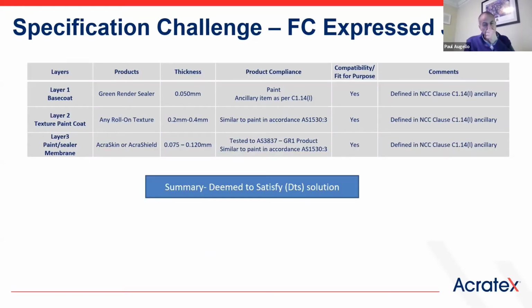The last one is the express jointed system, and this has probably got the most flexibility of all the substrates that are on the market at the moment, where I've got options of using a roll-on texture or a trowel-on texture, depending on what you're trying to achieve with this. But if you look at the system in its entirety, you've got a layer one, which is basically a primer undercoat. So that's an example being the paint under C1.14. You've got a roll-on texture to give you the aesthetic requirements. Again, the various finishes of different thicknesses. And then the last thing is that protective layer top coat, which will give you the weatherproofing to the total system for maintenance purposes over the long term as well.